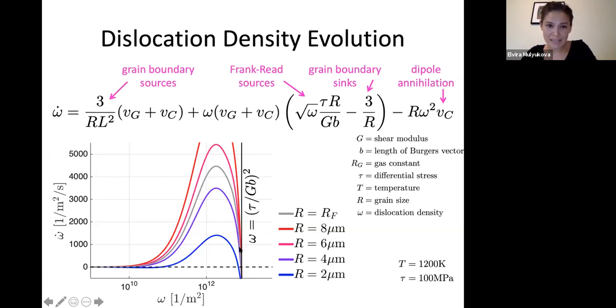It seems to not have any dependence on grain size, but it does depend on stress. This has actually been inferred theoretically previously and is also robustly observed in laboratory studies, to note again, deforming at relatively high strain rates, and sometimes also high temperatures. This empirical relation of dislocation density is entirely dictated by stress to some power. Here I'm only showing stress squared, and it is independent of grain size.